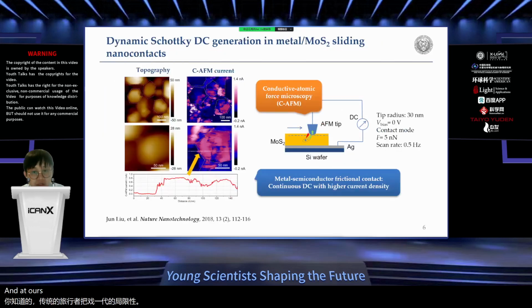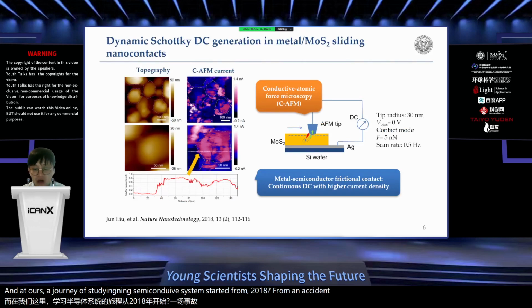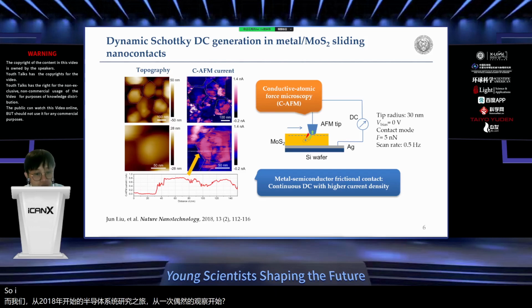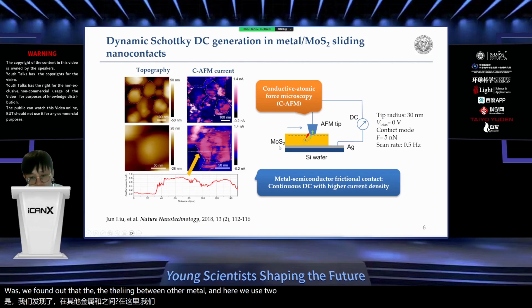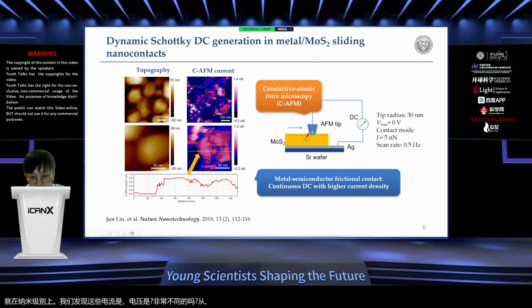And our journey of studying semiconductor systems started in 2018 from an accidental observation. So one day when I was doing this conductive AFM characterization, we found out that the sliding between a metal, and here we use a two-dimensional MoS2 system, the sliding between these two materials will generate a constant DC current from the nanoscopic level. And then we found that these currents and the voltage are very different from the previous AC one. You can see that it's always DC and also constant.